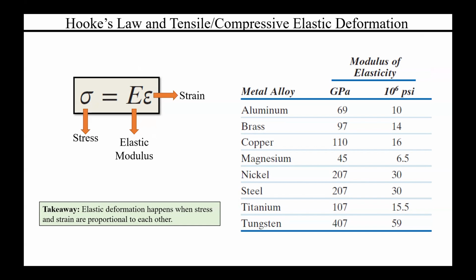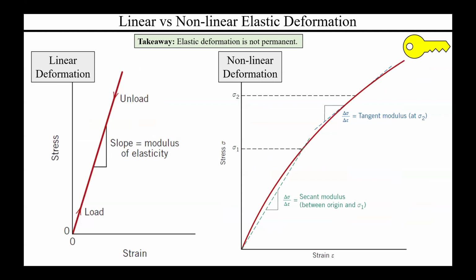But again, if you look at something like brass versus tungsten, you'll quickly find that tungsten has a nearly 4 times larger modulus of elasticity. What this means, again, in principle, is that you need to supply 4 times the amount of force on tungsten compared to brass in order to induce the same strain. So that's what this means. Again, you apply a load on the material, and the slope within that elastic region is your elastic modulus.